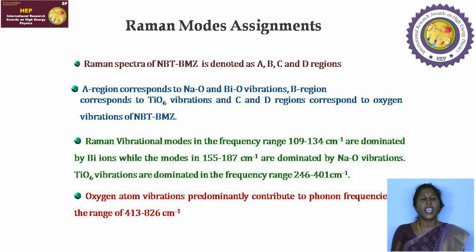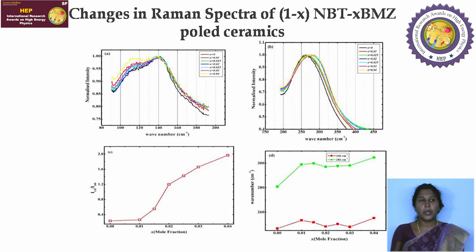But in our study, we can observe the ETO1 mode that belongs to BiO vibrations. Now, this figure shows the changes in the Raman spectra of (1-x)NBT and xBMZ poled ceramics. Here we are seeing the normalized intensity of the peaks in the A region as well as the B region.